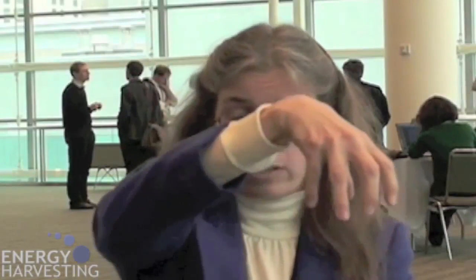When you have a domain wall like this, material elongated this way, this material elongated this way, when you shift the domain wall, it doesn't give you a lot in terms of piezoelectric response. But if you have a material that's elongated this way, beside a region that's elongated this way, and you can move that boundary back and forth, now you're changing the volume fraction of the material that's elongated this way. In bulk materials, domain wall motion accounts for typically 1/2 to 2/3 of the usable piezoelectric response. That's what matters to you. And associated with that is also hysteresis.